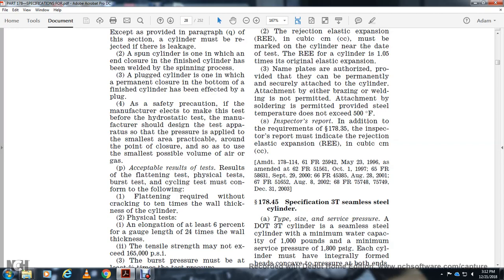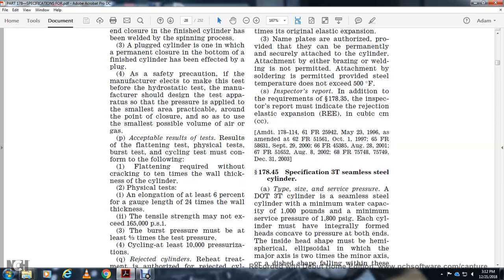And elongation of the gauge length must be 24 times the wall. The tensile strength must not exceed 165,000 psi. Burst pressure must be at least 5/3 times the test pressure, and pressure cycling at least 10,000 pressurizations.